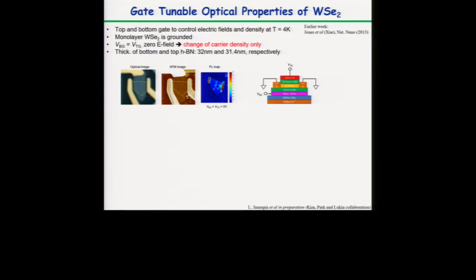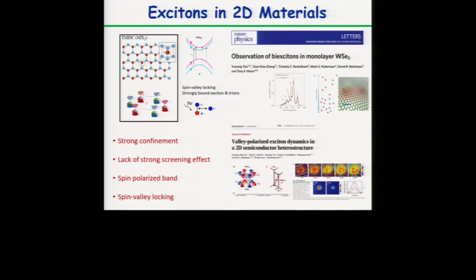What is the binding energy of the exciton, and what's the spatial dimension? So for a single layer material, the binding energy is around 300 millielectron volts, and the Bohr radius is a couple of nanometers.